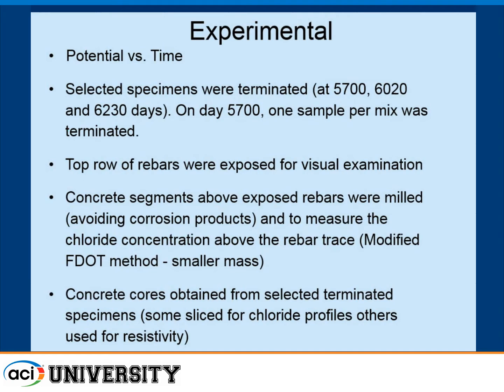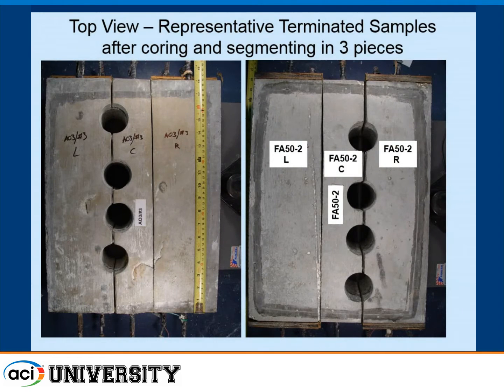In addition, before we did the cutting, we obtained concrete cores so that we can characterize the chloride profiles as a function of depth and also the resistivity of the specimens. So this is one of those specimens, and incidentally, at 5,700 days, this was the only one that actually showed some cracks, and is the one that contained only OPC.